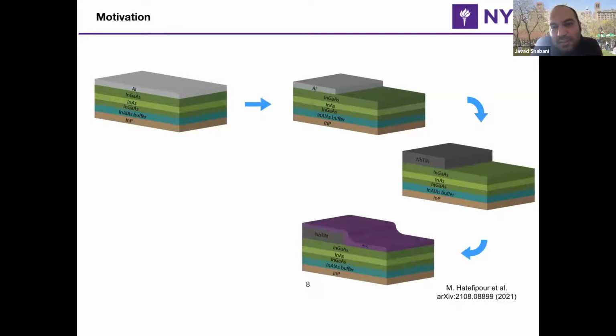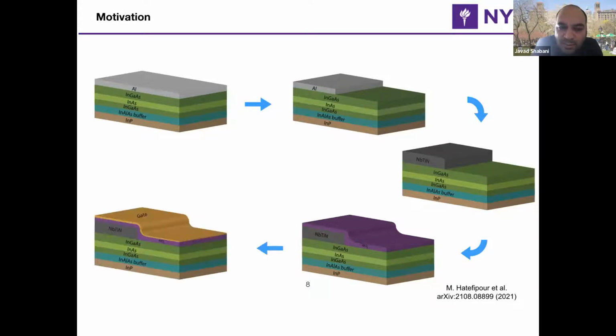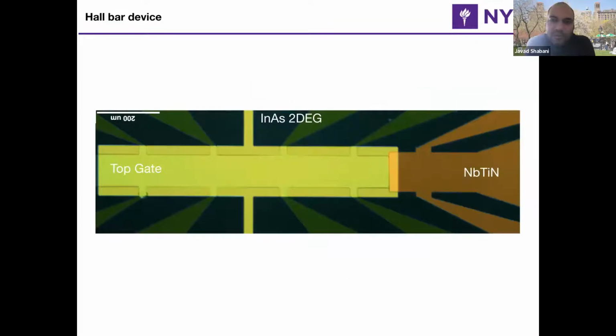When we put the system into the sputtering, around exactly at that point, we actually get the aluminum off and we put niobium titanium nitride. So this is already done in a controlled environment. After the etch of aluminum, the surface is not exposed to air. And when we put niobium titanium nitride, then you can basically go ahead and put an aluminum oxide and a gate on top. So that interface is pristine. It's not epitaxially pristine, but it has not seen air, at least in the usual sense that we expose it to the ambient, right?